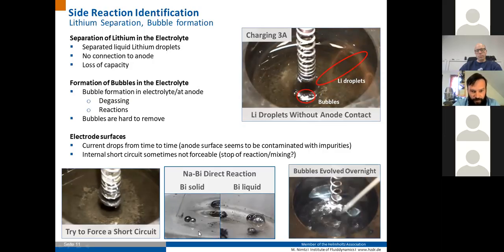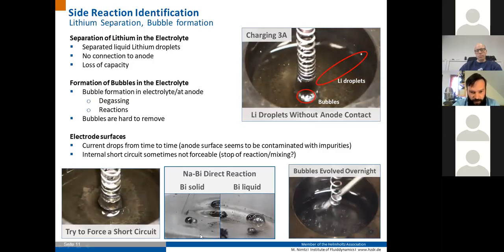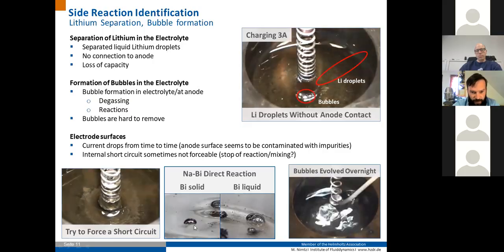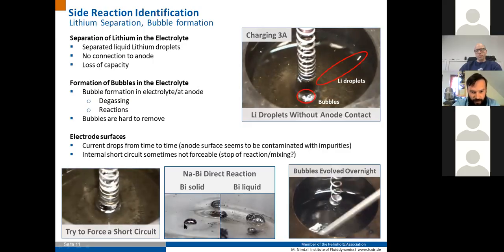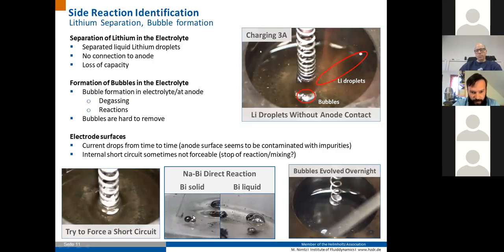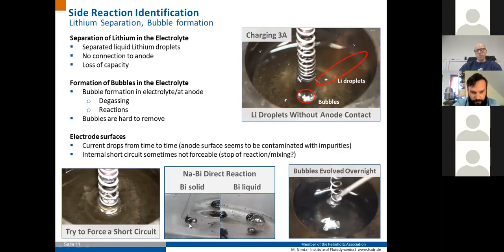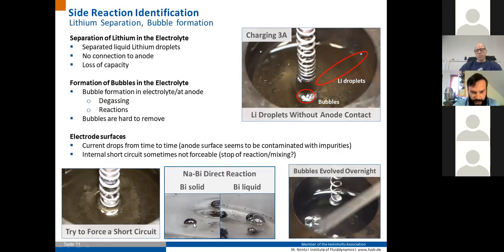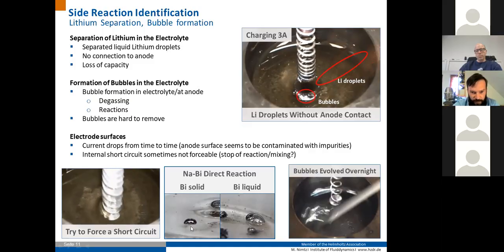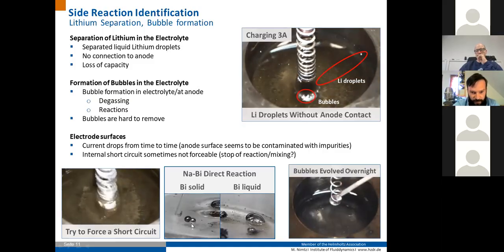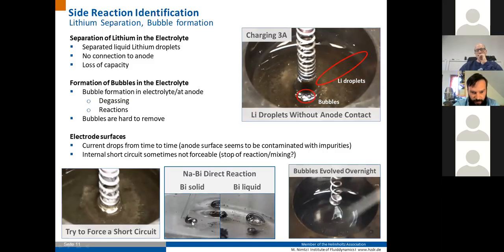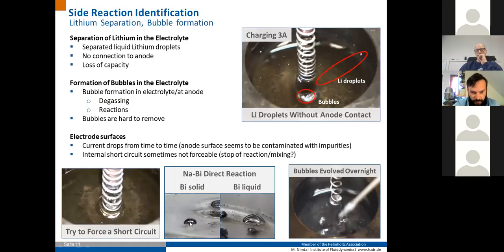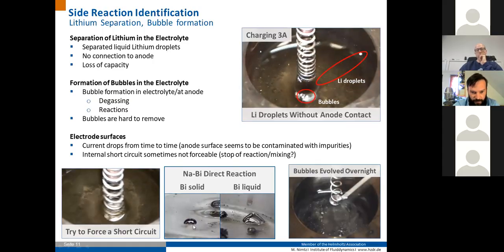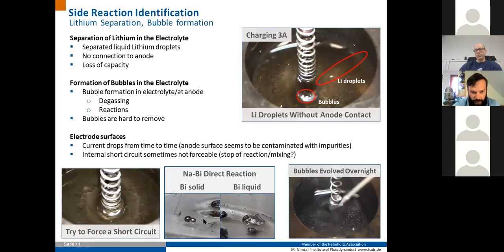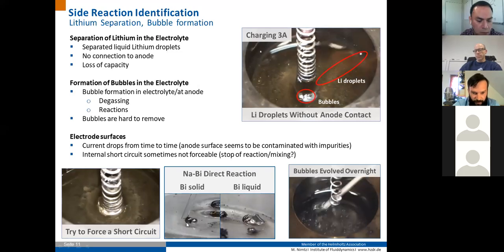The expected reaction can be seen here, where a solid bismuth droplet is reacting with a liquid sodium droplet. You can see the high reaction heat during the fusion of these metals to an alloy. The bismuth is glowing bright red.